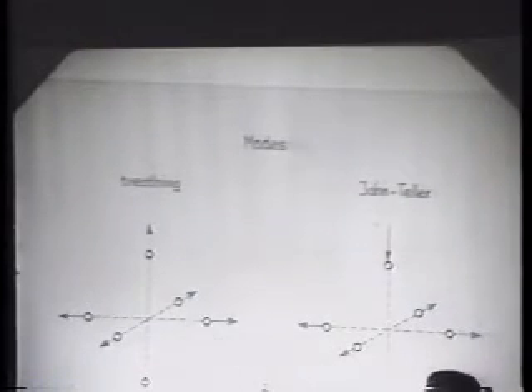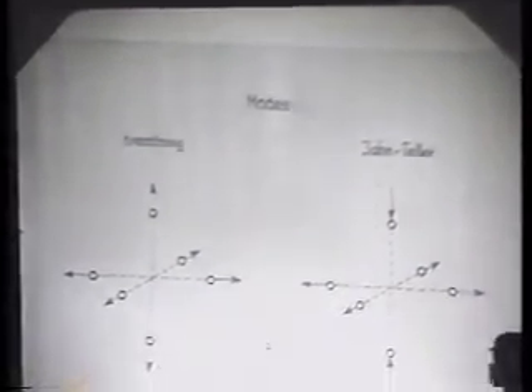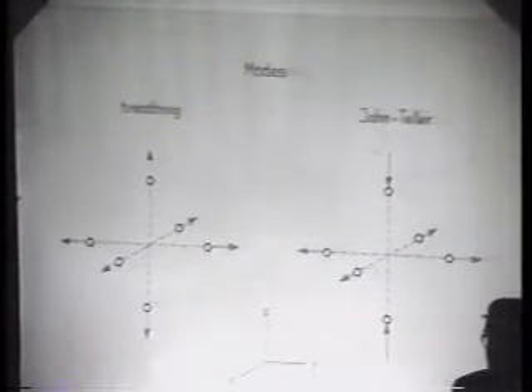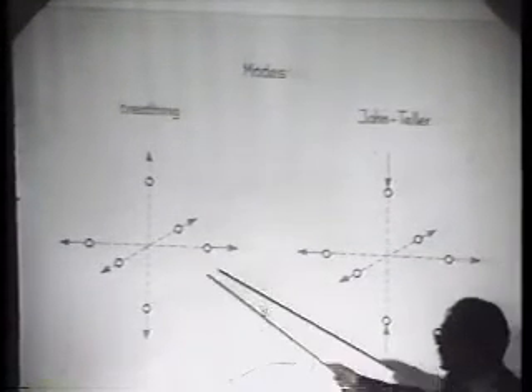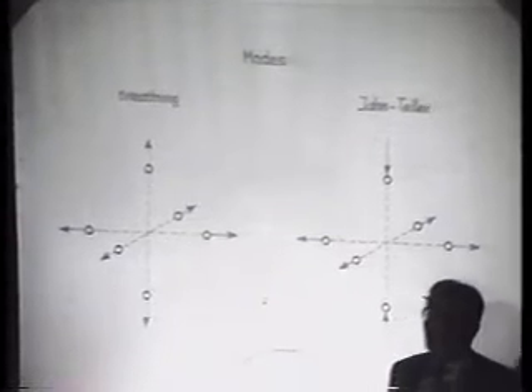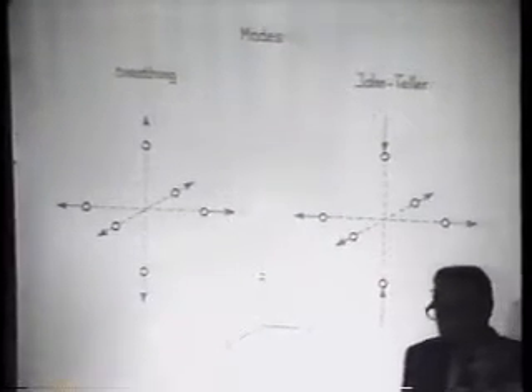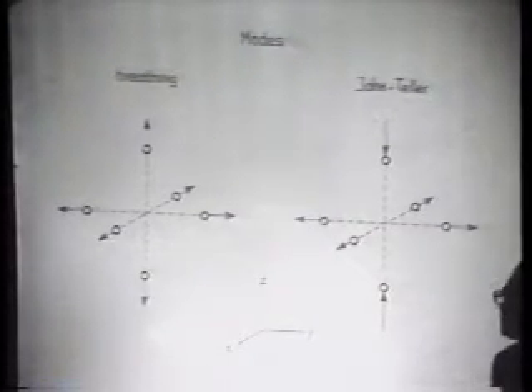How does the oxygen move? Well, you have basically two modes, a breathing mode and a Jahn-Teller mode. The breathing mode is shown here. It changes the volume. And the breathing mode is very attractive if you have, say, bismuth or lead, like in the bismuth-lead perovskite, because the bismuth and the lead tend to disproportionate. So this is a disproportionating mode in a way.